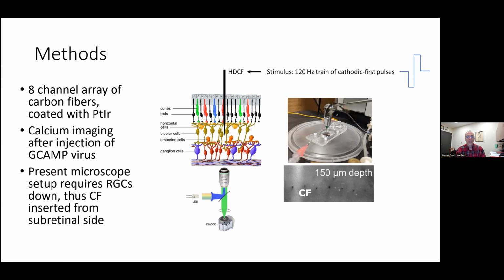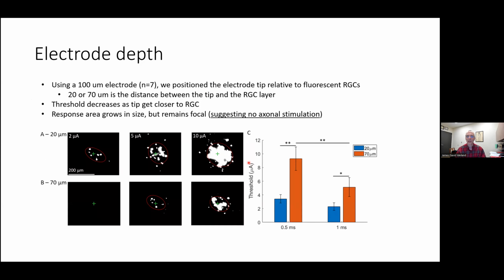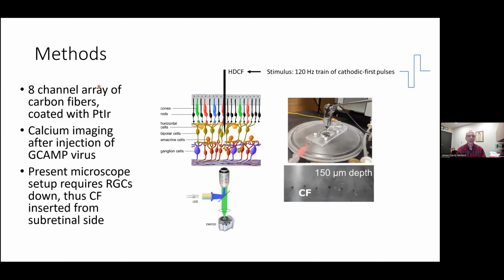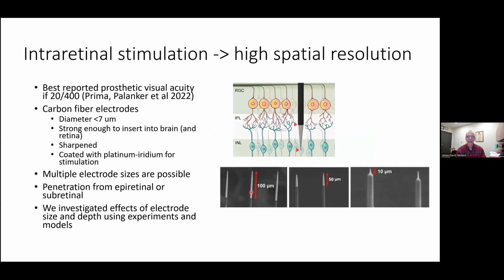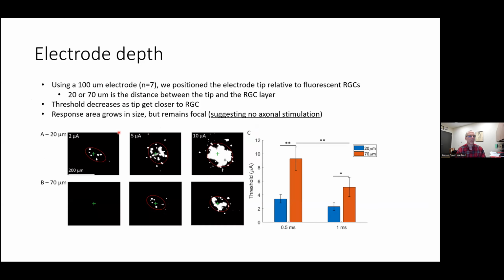So that allows us to electrically stimulate and then record from literally hundreds of retinal ganglion cells by measuring their fluorescence. What's shown here is the view through the inverted microscope of the tips of the carbon fibers as they were inserted into the retina. There's a mouse retina in this dish. You really can't see it, but this is the holder for the carbon fiber array. So using these electrodes, we had a 100 micron electrode. What I mean by that is that the exposed length of the electrode is 100 microns. So that's what that term means.